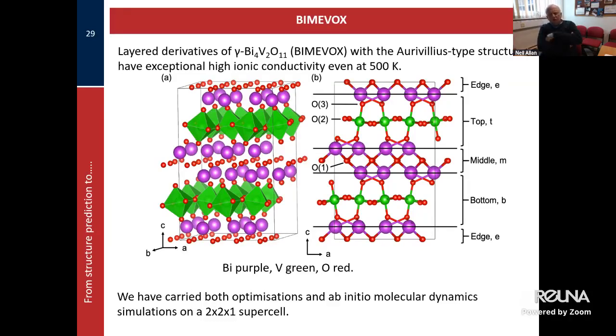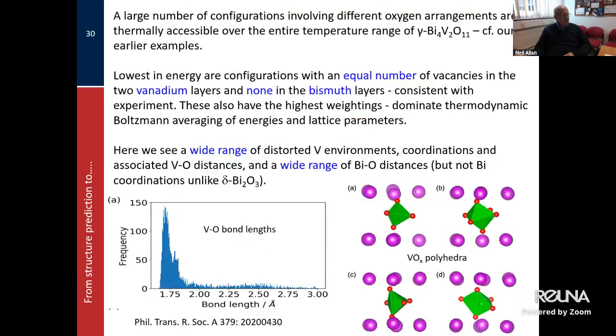Because we'd worked on the local structures and the local environments in the delta form of bismuth oxide before, and rationalized the conductivity there in terms of the ready distortions and the local environments of the bismuth ions, I said, well, I don't think the vanadium is doing anything special. It's all in the bismuth. We'll find it's all in the bismuth layers. Actually, even the structure wasn't fully resolved in the literature. Very little was understood about this structure.